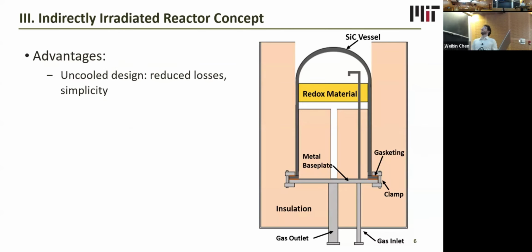The advantages of such a system are that it is an uncooled design. We previously looked at reactor designs that involve an infrared transmitting window, but our preliminary modeling showed that this requires some level of active cooling in the system and very high heat losses due to the properties of infrared transmissive materials. This design does not use any of that, and it would result in reduced losses and also engineering simplicity, because this would eventually be a moving reactor, and it would be very hard to have an active cooling system in it. It's also expandable and modular. You can stack these silicon carbide vessels next to each other in order to obtain a larger reactor.